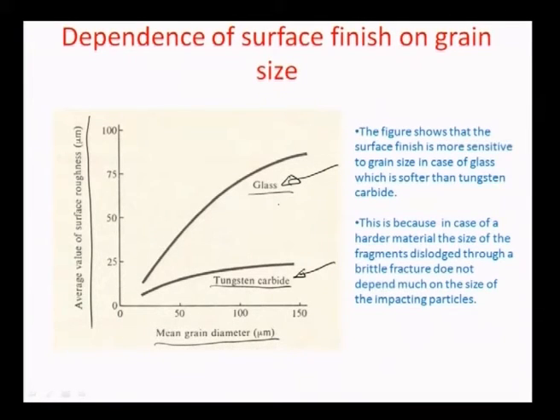But what is important to see here is that if the surface is more brittle, then the surface roughness value which would eventually arise would be higher in comparison to a harder material, for obvious reasons: a brittle material would be more amenable to brittle fracture, and greater chunks of material would come out and form larger craters, and because of the larger craters the overall average roughness of the surface would be higher.